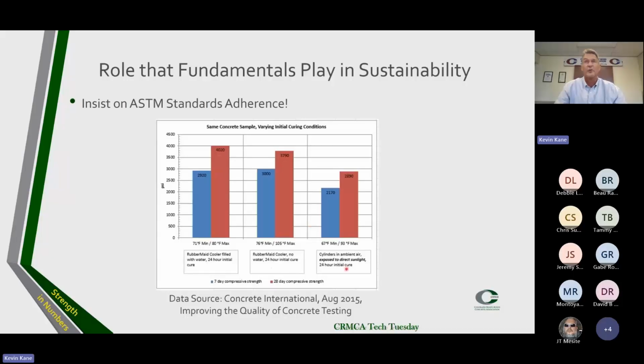And then worse, if you just take the cylinders and leave them in direct sunlight. We have pretty intense solar radiation here in Colorado. Look what happens. It was only 93 degrees that day, but these cylinders were left out in the sun, and look what we did to our compressive strength compared to the properly cured cylinders. So we must insist on adherence to ASTM standards. And I know everybody's been hearing it forever. We're going to keep beating the drum until we get 100% compliance, because it's all for nothing on sustainability if we don't do the testing correctly.